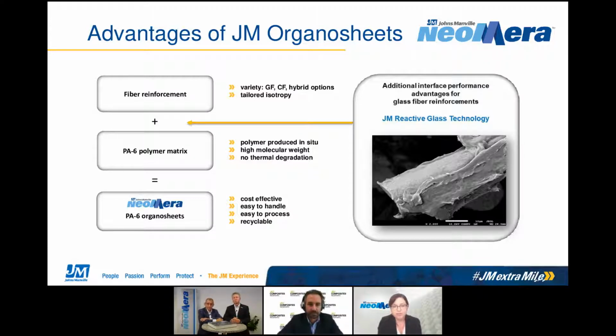The organosheets also have advantages coming from the polymer. As I said earlier, it's produced in situ, it's high molecular weight. And what's very interesting is that this PA6 has never seen an event that can lead to thermal degradation. We are making it at about 150 to 170 degrees Celsius, and melting is over 210 to 220. So this polymer has never been melted, has never been degraded. That's a huge advantage.